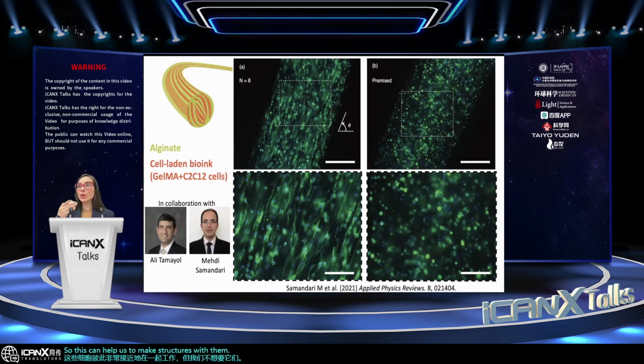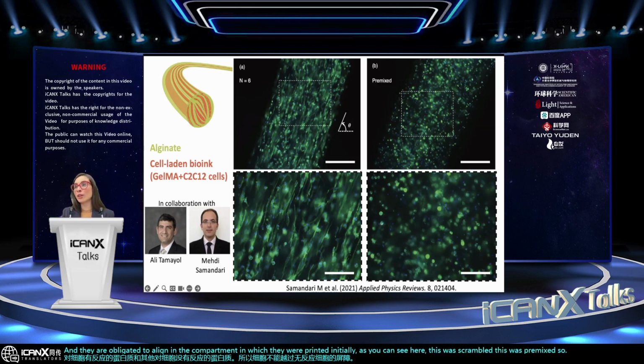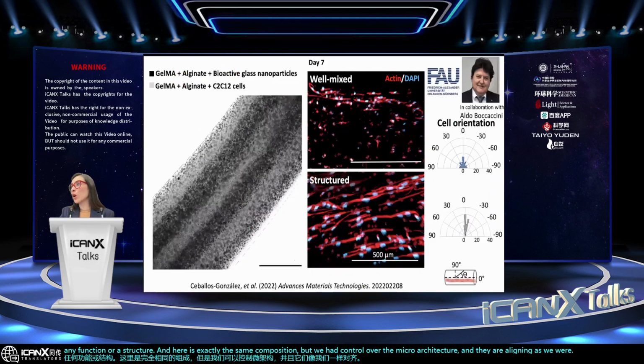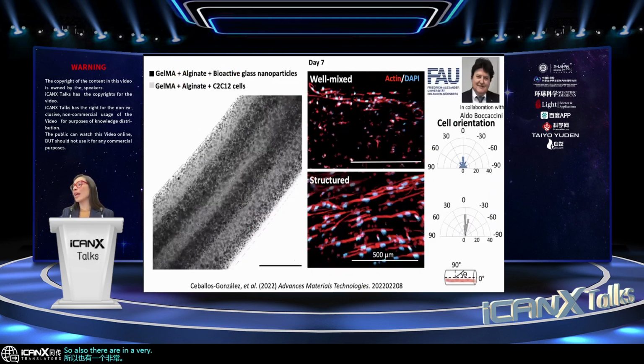For example, in this case, we alternated inks that were responsive to cells and other inks that were not responsive to cells. So the cells cannot cross the barriers of the non-responsive inks, and they are obligated to align in the compartment in which they were printed initially. As you can see here, this was scrambled, this was premixed, so we cannot see any function or structure. And here is exactly the same composition, but we had control over the microarchitecture, and they are aligning as we expected.